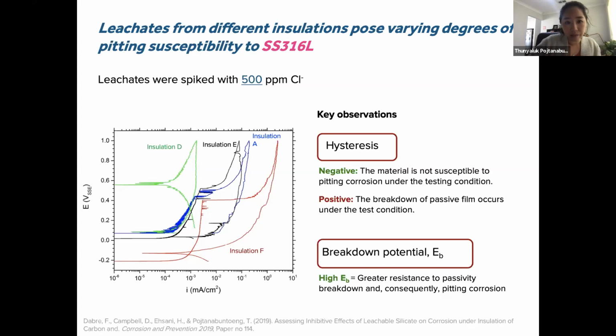So here, there are a few features on the cyclic potentiodynamic scan that we generally look at. The first one is called hysteresis. Insulation D is what we call a negative hysteresis, and that means the material is not susceptible to pitting corrosion because the reverse scan has a lower current compared to the forward scan, meaning that the passive region of the stainless steel was still intact even after polarizing anodically.